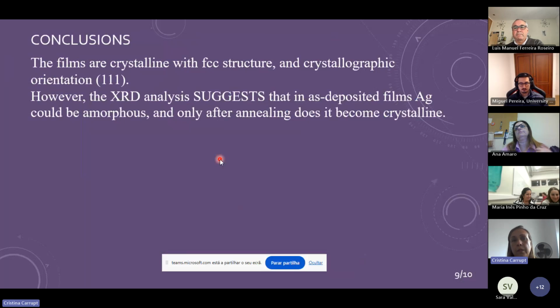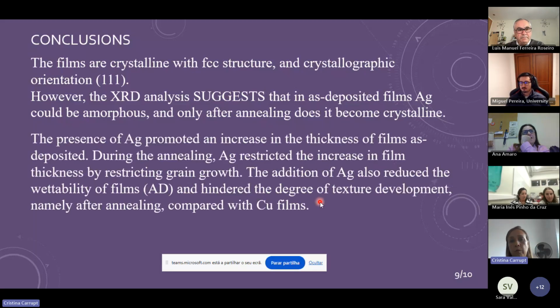So, some conclusions. The films are crystalline with FCC structure and crystallographic orientation according to plane 111. However, XRD analysis suggests that in the as-deposition film Ag could be amorphous, and only after annealing does it become crystalline. The presence of silver promotes an increase in the thickness of films as deposited. During the annealing, silver restricts the increase of film thickness by restricting grain growth because of the diffusion of silver